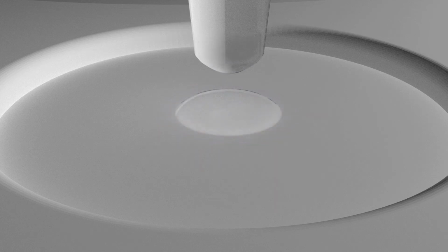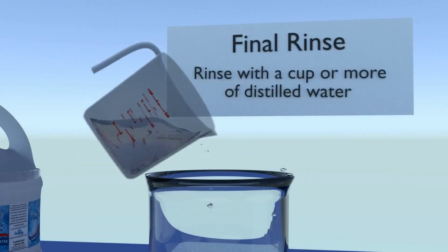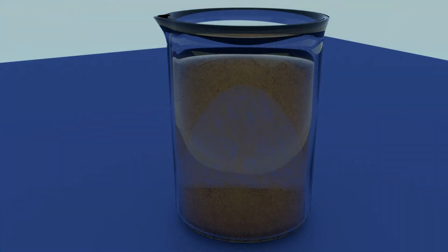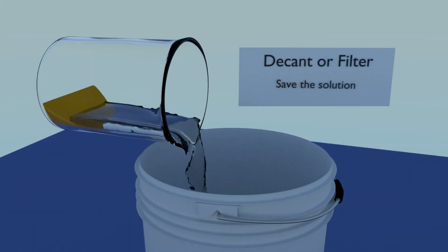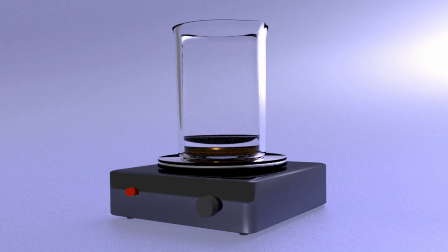When the ammonia test indicates no color change, it's time to give your mud a final rinse with distilled water. The distilled water will wash away any minerals left behind by your tap water. Add a cup or more of distilled water. Give your gold mud some time to settle. Then filter or decant your water. You can now dry your gold mud, either by air drying or heating on a hot plate. Please note, do not put a cold beaker on a hot plate. It will shatter.